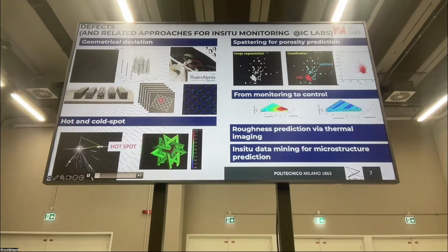Clearly, I will not have enough time to describe everything, but there are a lot of papers we have written in this direction of video imaging, in which the main job is to find hot spots and cold spots. A hot spot means a spot that remains hot for a long time. You will see that while the laser is doing its job of melting, when it stops in one specific corner, this corner remains with high intensity for a long time, and this is going to be a defect. So by detecting this hot spot in real time, this can create an advantage.